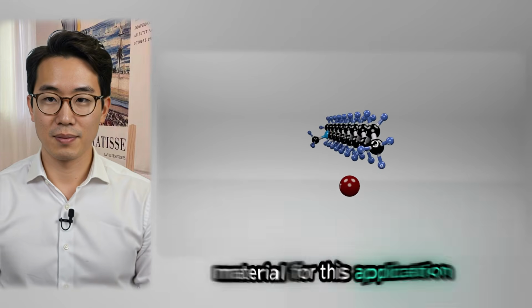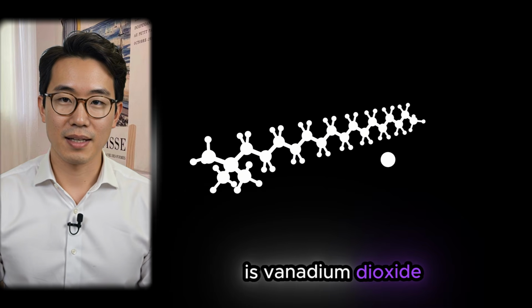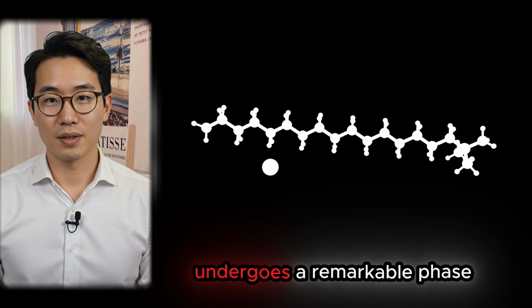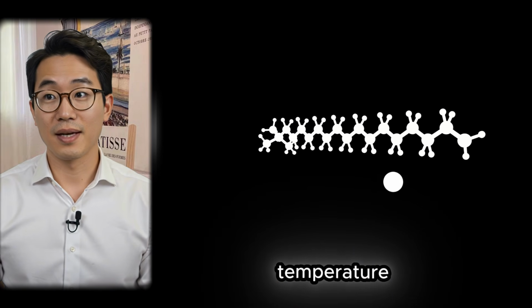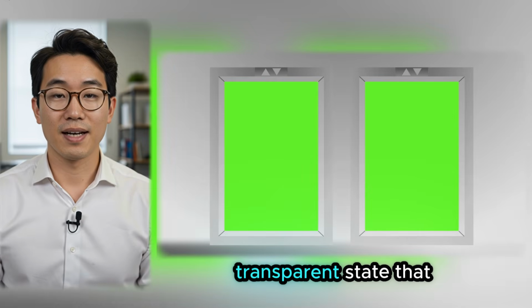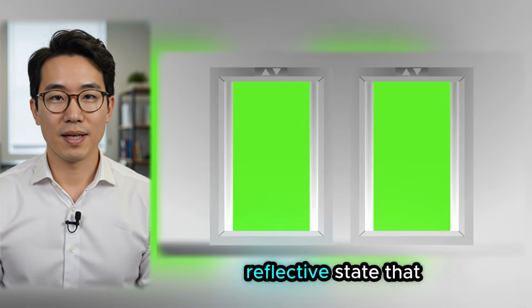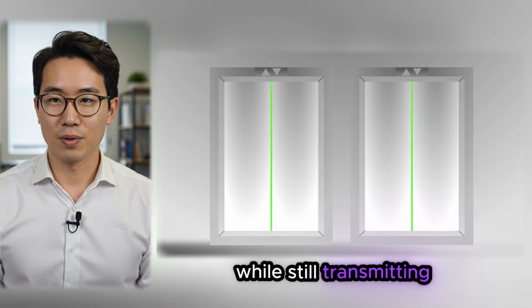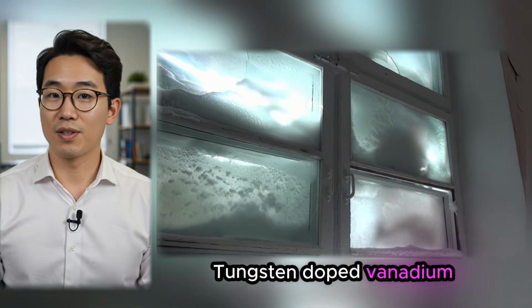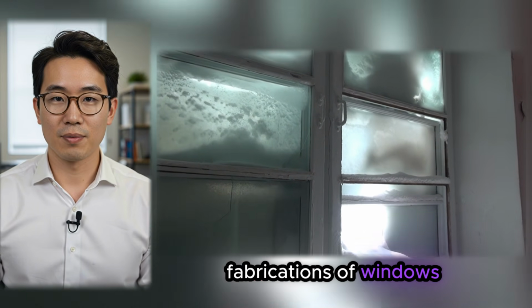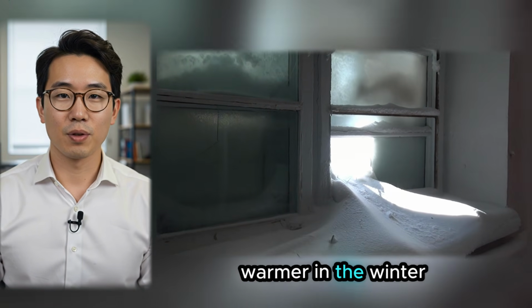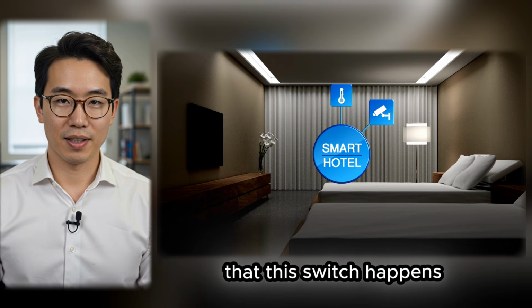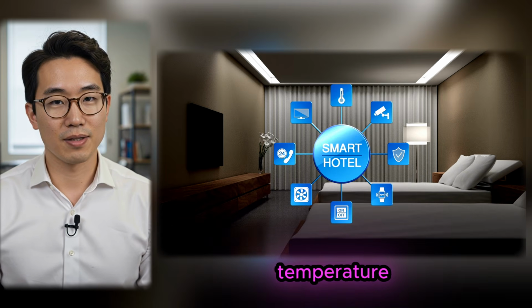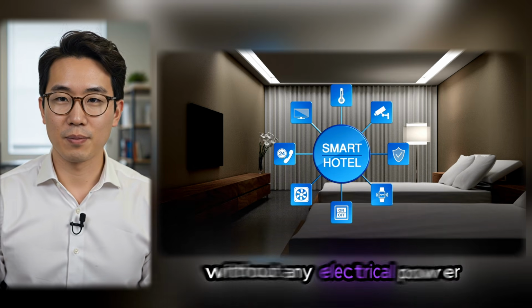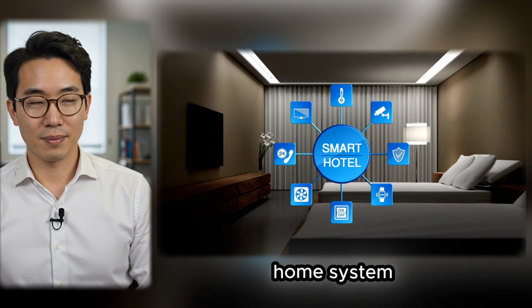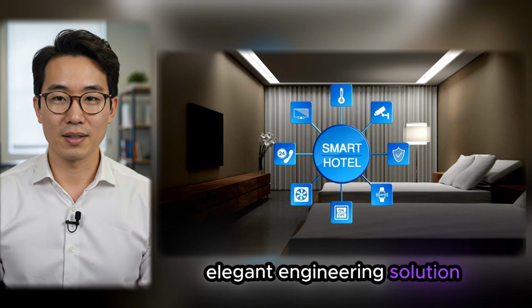The most widely researched material for this application is vanadium dioxide, a metal compound that undergoes a remarkable phase transition at a specific temperature, shifting from a transparent state that allows infrared light through to a reflective state that blocks infrared while still transmitting visible light. Tungsten-doped vanadium dioxide allows fabrications of windows that might be cooler in the summer and warmer in the winter, and the fact that this switch happens automatically in response to temperature without any electrical power, without any wiring, without any smart home system, makes it a genuinely elegant engineering solution.